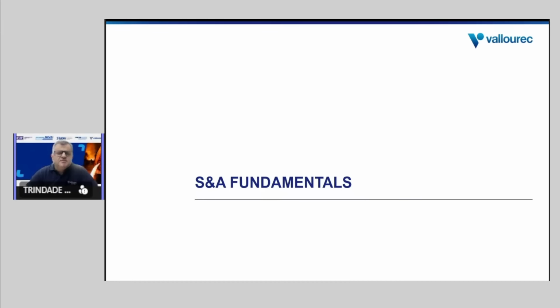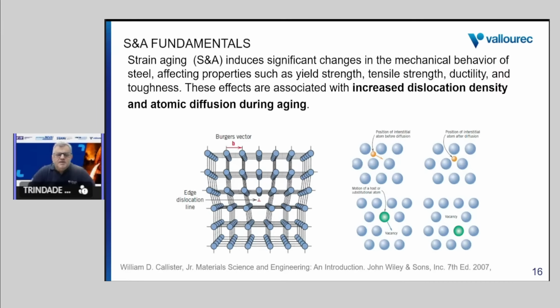So what are the fundamentals for that? We know that when we introduce plastic deformation in the steel, of course we create defects, and one of these defects, very important, is dislocations. So you increase the dislocation density of the material, and if you submit this material to aging, we create mobility of the atoms, and then of course you are going to have diffusion, mobility of interstitial atoms, vacancies, and substitutional atoms. So this should happen in the material: plastic deformation creates dislocations and defects, and during aging, atom mobility should happen.